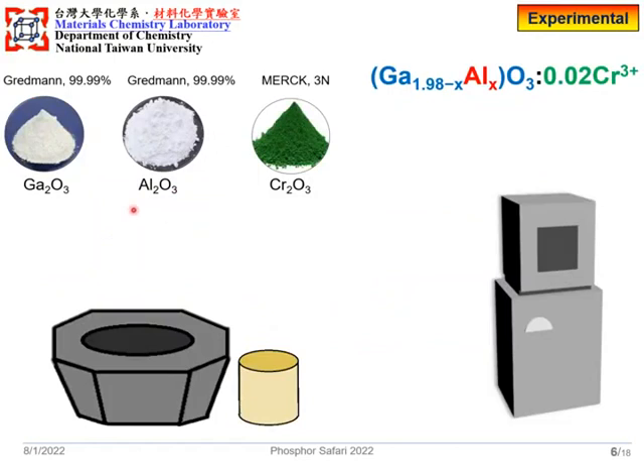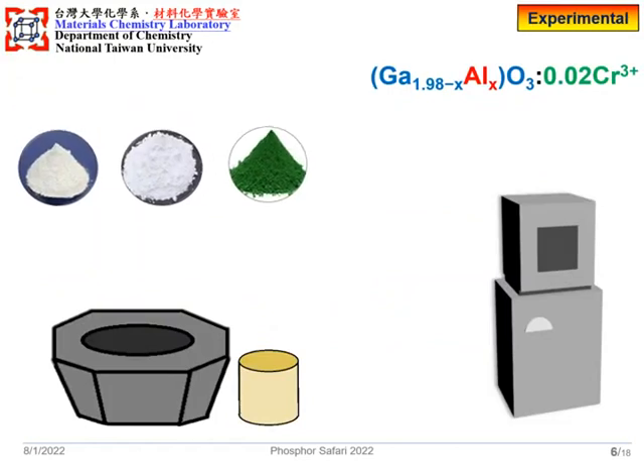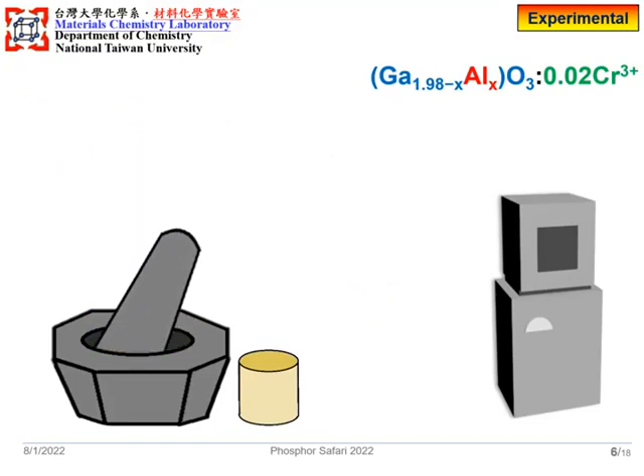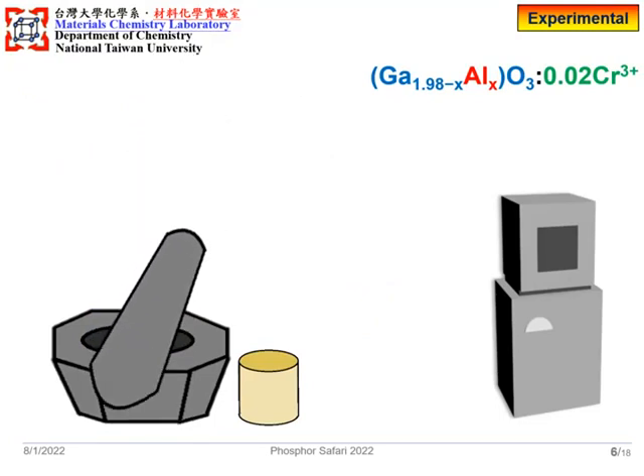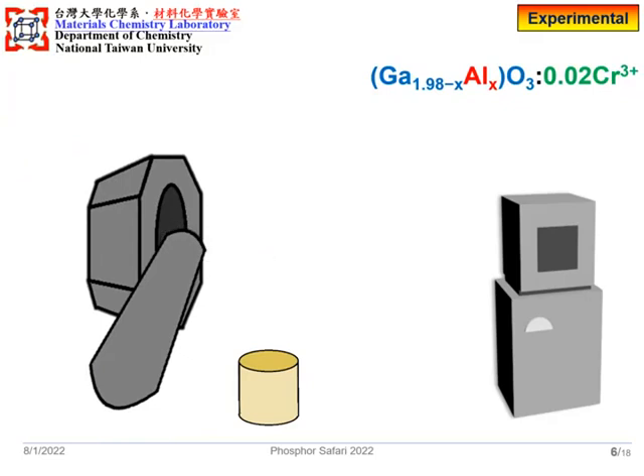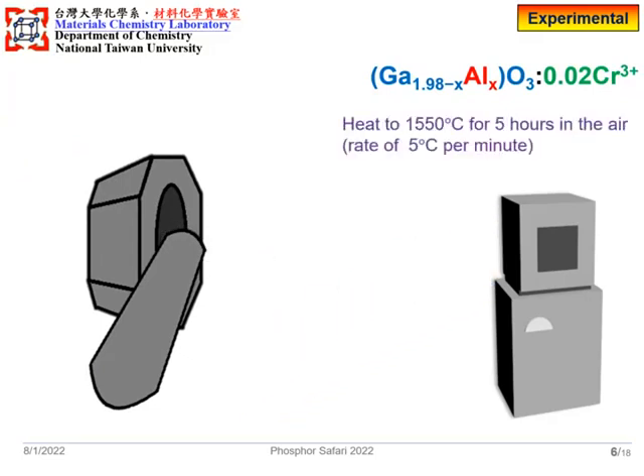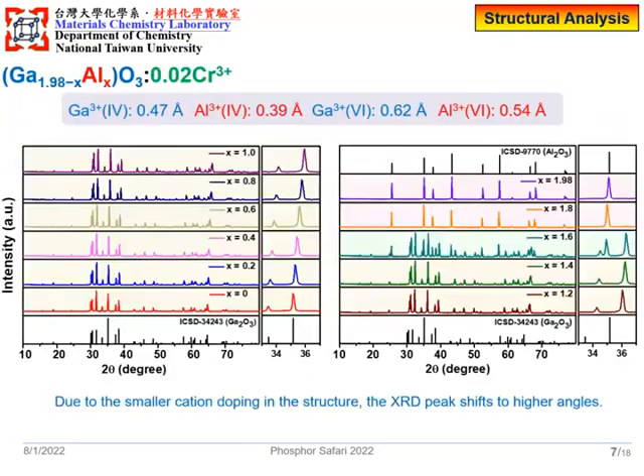First, we weigh our precursors based on stoichiometry and transfer them into the mortar. Second, we grind the powder for 20 minutes. Third, we put the powder into the crucible and sinter it in the furnace for 5 hours at 1550 degrees in the air. From the XRD result, we can find out that the peak shifts to the higher angle due to the lattice shrinkage, which means the aluminum gets into the structure successfully.